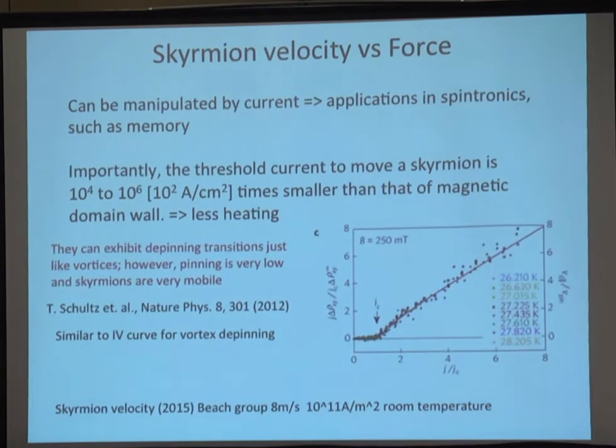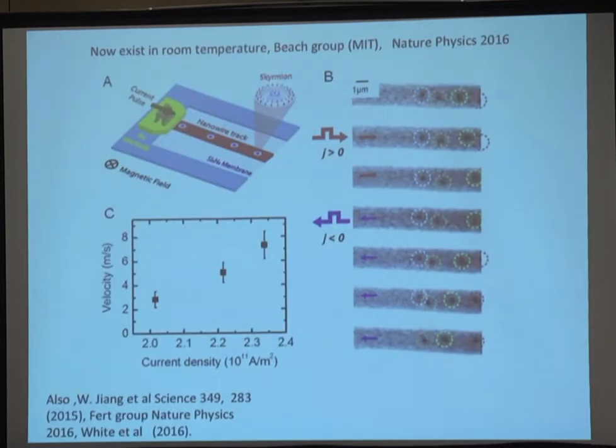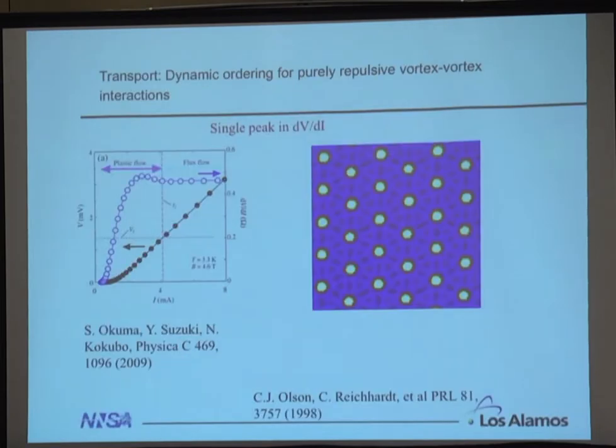Lynn showed that you can essentially make a skyrmion velocity versus applied force curve, and this would be equivalent current to the depinning of the skyrmion, and then the skyrmion starts to move very rapidly. The other way to get these velocity-force curves is just with direct observation. So here's the applied pulse, and you can then measure your skyrmion velocity versus your critical current, out of the Beach group at MIT. People have done this as well.